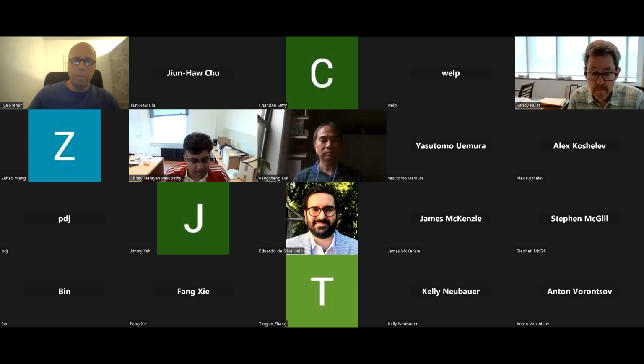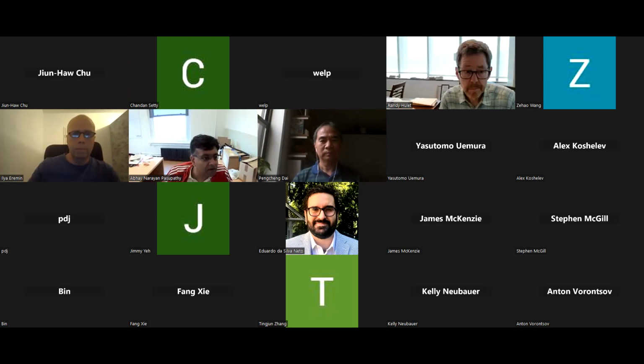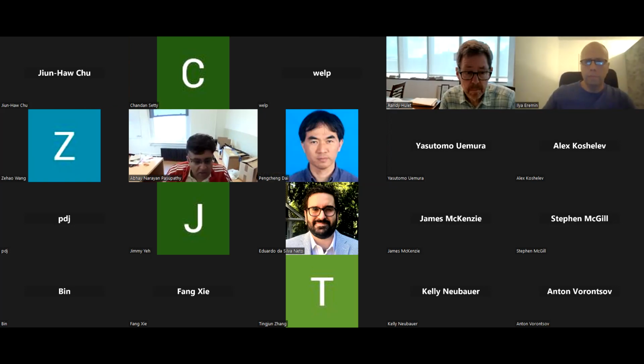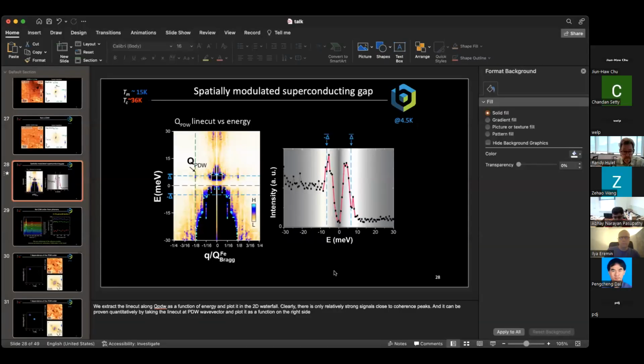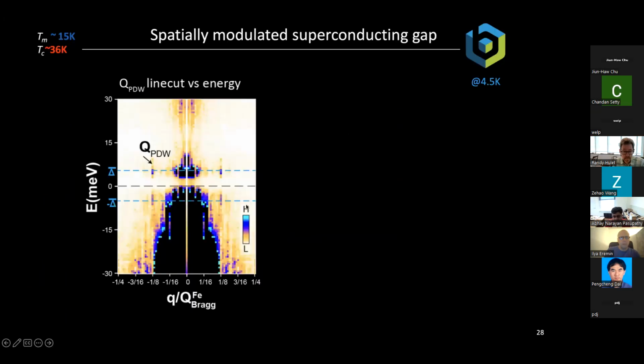Let me see if I can pull up the slide to show you the energy dependence. I went through that a little bit quickly. Okay, let me put it in full screen. So this is energy along the y-axis, and this is wave vector. So this is a cut through that direction of the modulation, and you see the intensity of this feature only around the coherence peak energy. So this is 7 millielectronvolts or something like that. But as you go to much higher energies, this is all just noise, and there's nothing on the other side. So it's really around the superconducting energy scale that we see this feature. Okay. Does that make sense?